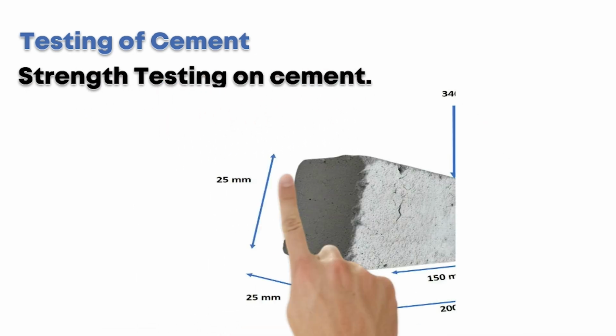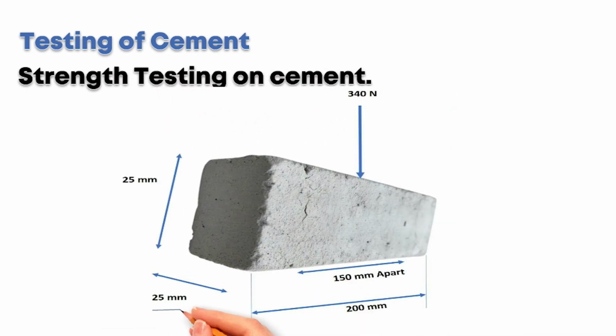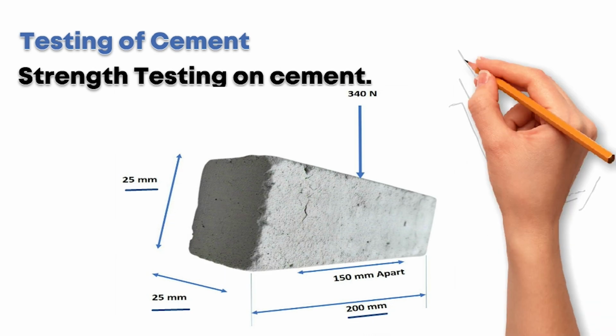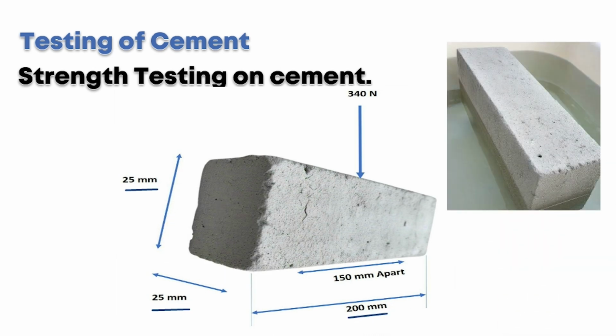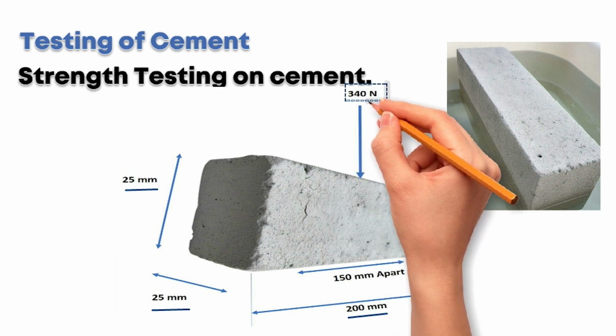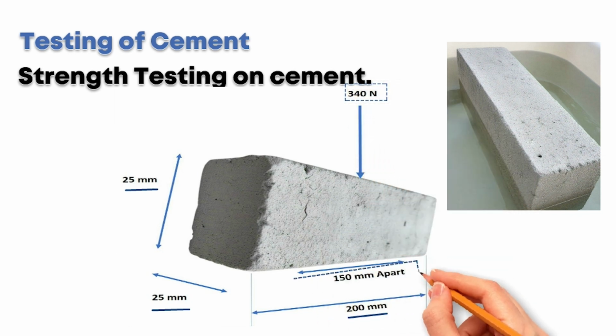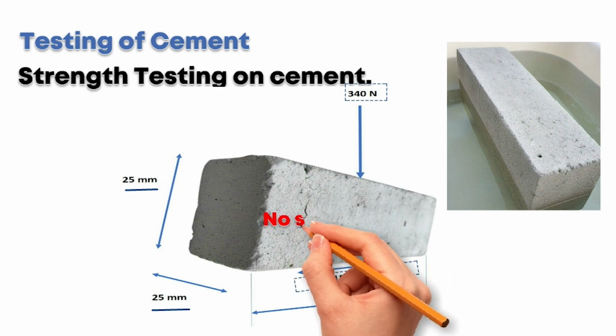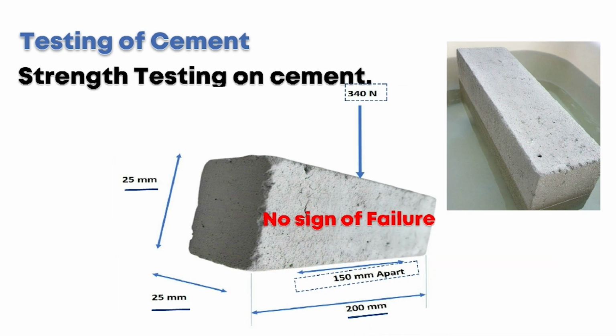The strength test on cement. Prepare a block of cement to be tested of size 25 mm by 25 mm by 200 mm. Immerse the block of cement in water for 7 days. Subject the block to a point load of 340 N by placing it over a support of 150 mm apart. The sample should show no sign of failure under the application of load.